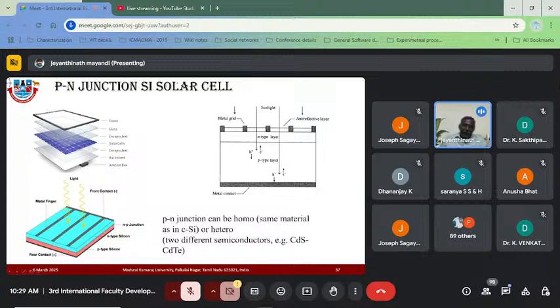Here you can see the schematic structure of a solar cell. It contains a p-type silicon layer and an n-type layer. How it is made is you take a silicon wafer which is doped with either phosphorus or boron. If it is doped with phosphorus, then it's n-type silicon, and if it is doped with boron, then it is p-type silicon. In normal cases, we take a boron-doped silicon wafer, and then we diffuse phosphorus on top of the surface, and then we make an anti-reflection coating. The anti-reflection coating is mostly made from silicon nitride layers, around 80 to 120 nanometers.